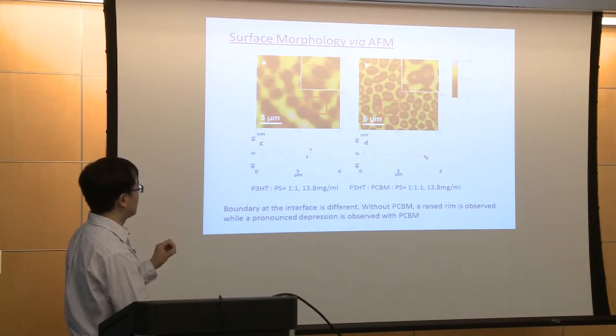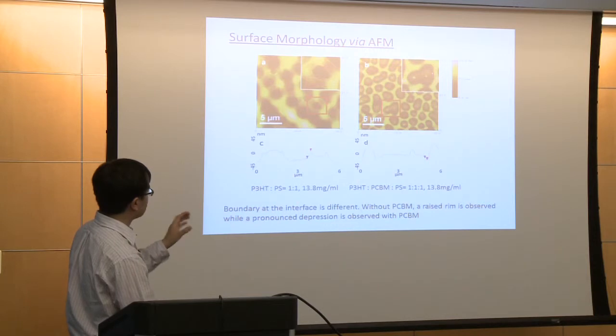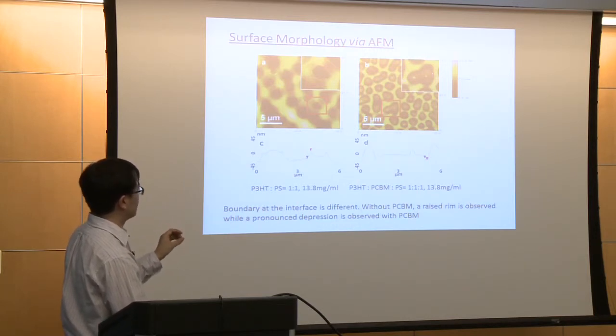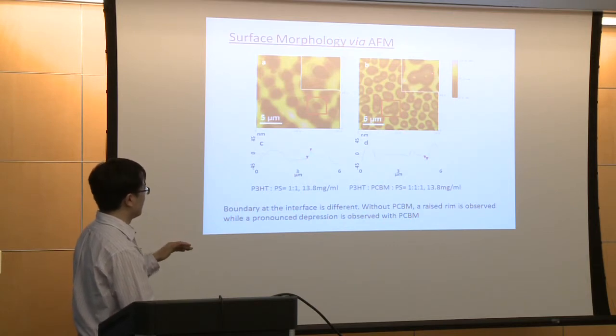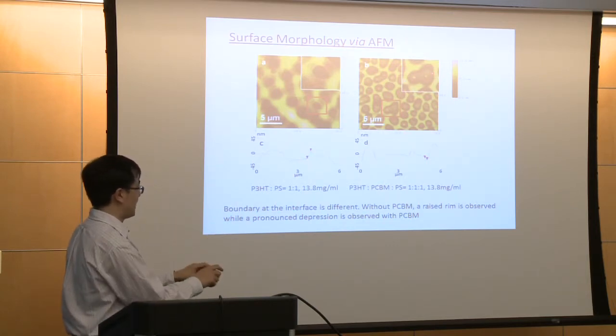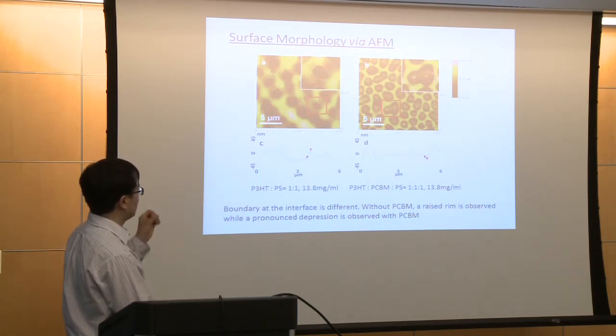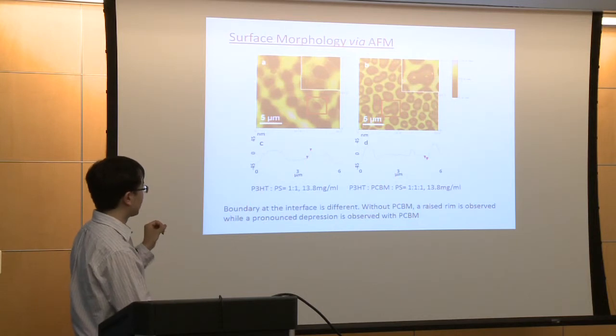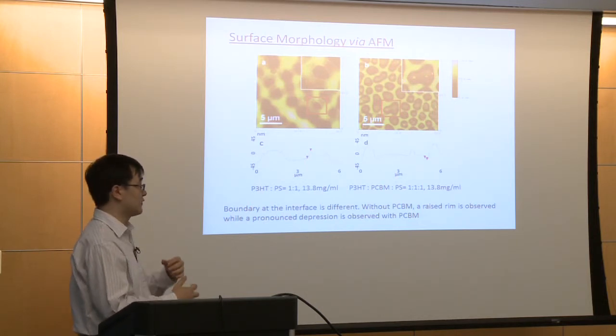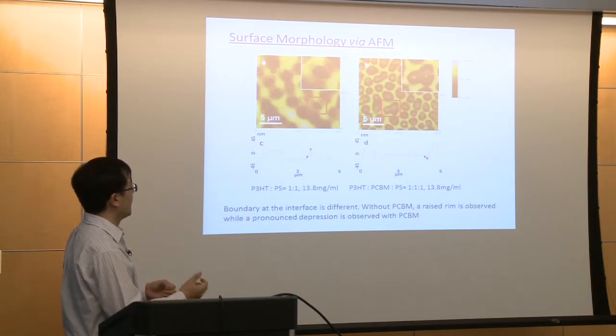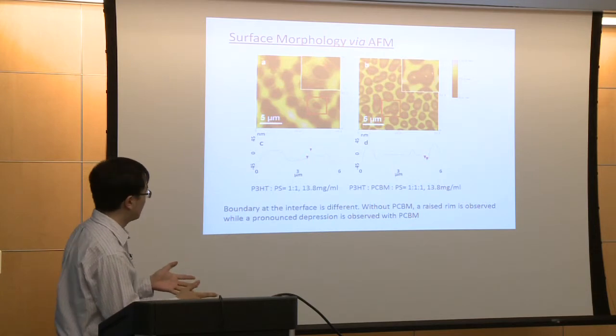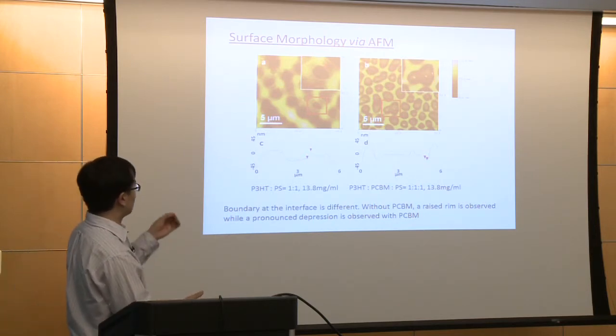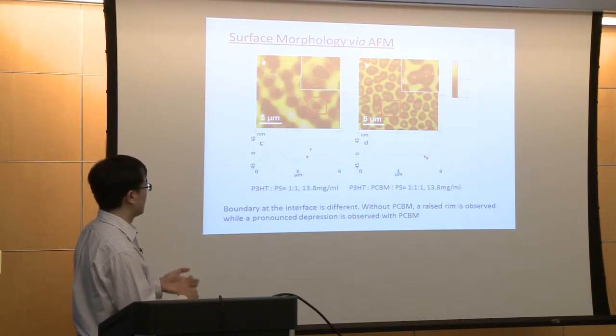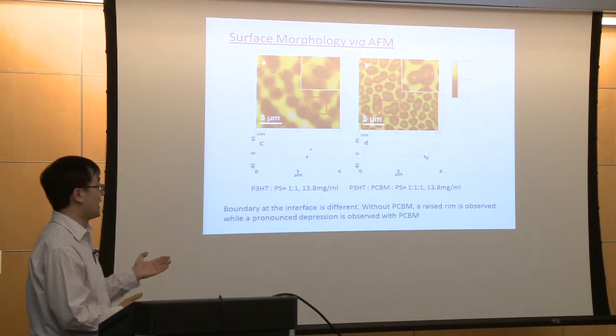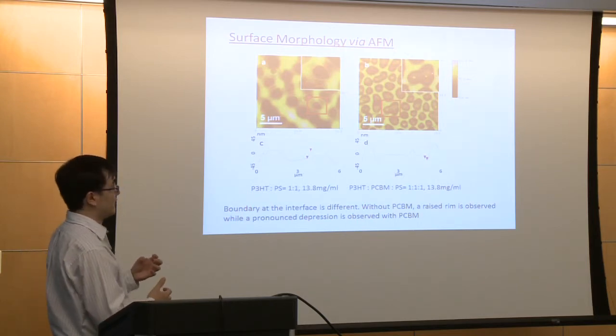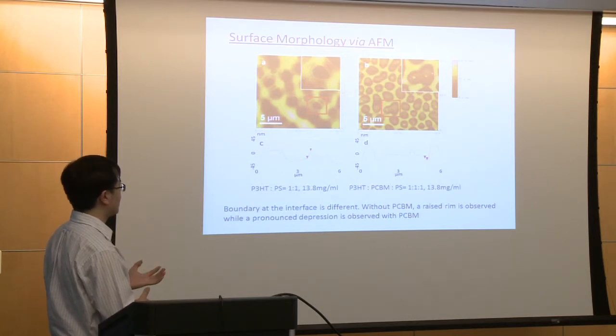After we put some PCBM into the system, we can see a significant difference at the boundary. There's a depression at the boundary, which means the boundary is lower than the middle part or the outer part. So we assume there's PCBM segregating at the interface, and because of the repulsive interaction between PCBM and the polystyrene, the PCBM will exclude polystyrene into the outer phase. In this way, the depression at the boundary will happen. But this is just an assumption. This is just kind of indirect evidence that PCBM will segregate at the interface.